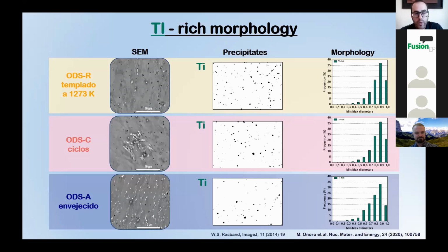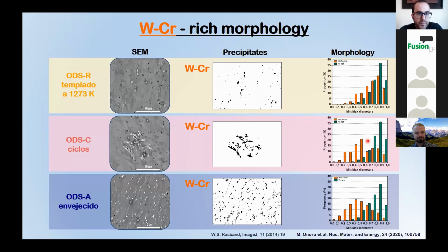From the morphological point of view, we analyzed secondary phases individually. They were fitted as ellipses, and we estimated the maximum to minimum diameter ratio. The round-shaped nature of titanium-rich precipitates prevails after the three different thermal treatments. On the other hand, the tungsten-chromium-rich precipitates started with a round-shaped nature after annealing, broadening for both cycling and aging treatments. Furthermore, the aging treatment promoted their diffusion along grain boundaries that could be related with the loss of total elongation reported on tensile test.